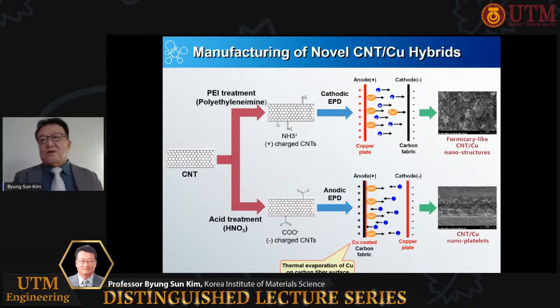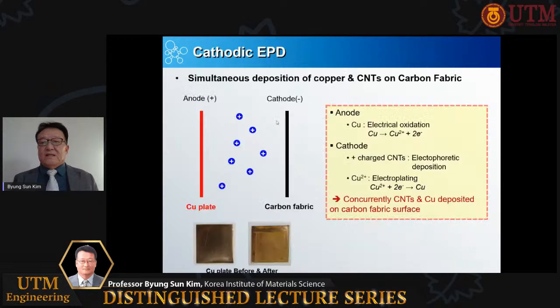In manufacturing of novel CNT copper hybrid, there are two ways to treat carbon nanomaterials, such as CNT. In cathodic EPD process, as shown on top portion of this flow diagram, CNTs are PEI treated to have plus charge. Then these CNTs via EPD process will be deposited on the surface of the carbon fabric to produce formicary-like CNT copper nanostructures. In anodic EPD process, CNTs are nitric acid treated to have minus charge. Then these CNTs via EPD process will be deposited on the surface of copper-coated carbon fabric to produce CNT copper nanoplatelets. In next few slides, the EPD processes will be discussed in more detail.